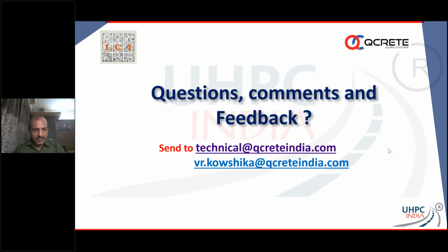No, the IS code presently doesn't have a mix design for UHPC, and nobody gives a very clear criteria on UHPC mix design. But as a material scientist, you will have to start somewhere. The best way to look at it is, number one, look at your particle packing. Your cement, your sand, whatever you're putting in, the pozzolans, etc. You want to have a very tight particle packing. If you are able to come up with a very tight particle packing, I think you are going to come up with a very good UHPC. That's the first fundamental part of designing a good UHPC.